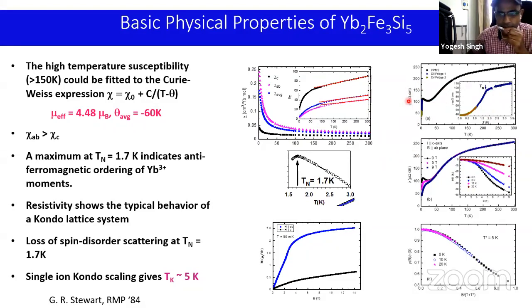So to get an estimate of the Kondo temperature, the standard procedure is that you look at the magnetoresistance, because the magnetic field will try to suppress the Kondo effect. So the upturn is suppressed when you apply a magnetic field. So MR versus field is plotted here at various temperatures. And if this behavior is governed by a single temperature scale, then all of these data can be collapsed onto a single one if you plot it as magnetoresistance versus B divided by T plus T star, with the appropriate T star. So we see that there is a beautiful collapse when T star is 5 Kelvin. So the Kondo temperature seems to be 5 Kelvin.